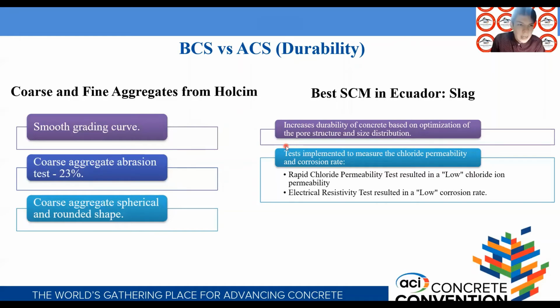With this data, now it's necessary to justify the difference between the alternative case and base case in terms of durability. And the answer is the improvement gained by substituting cement with the slag, whose selection was developed considering its availability in the country and the pollution it generates through production processes of the factories. The addition of the GBS gives an optimization of the pore structure and size distribution, densifying the mixture, making it less permeable to external agents and reducing the risk of sulfate attack, alkali-silica reactions, and chloride penetration.